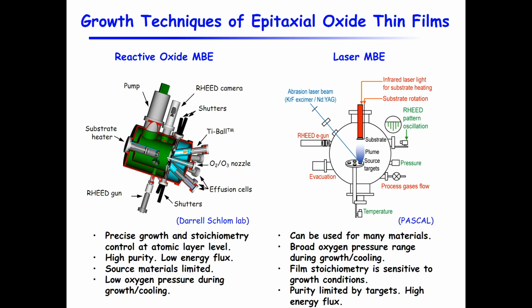The two most successful techniques are shown here. One is reactive oxide MBE, taken from Darrell Schlom's lab. You have different sources of elements in a UHV environment, with real-time monitoring of growth, and that has proven to grow very high quality films with great crystalline perfection. The problem is the limitations: they can only operate at low oxygen pressure. They can use ozone, but that's still limited to low oxygen pressure. Also, all these metal sources have to have somewhat similar properties: if some elements want more oxygen and some hate oxygen, you cannot put them together. It's also limited in that you cannot use it for some d and f electron elements, and so on.